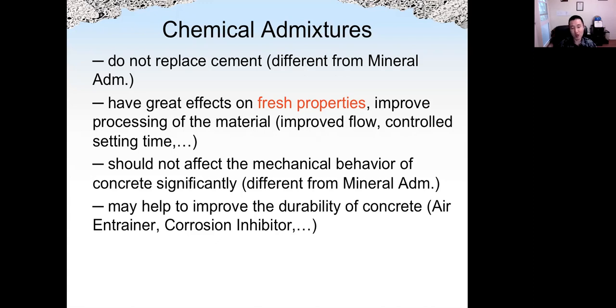So chemical admixtures do not replace cement. So this is one of the major differences from mineral admixtures. So for mineral admixtures, for example, fly ash typically replaces 10, 20, 30, or even more percentage of Portland cement. Okay, but for chemical admixtures, they do not replace cement. Okay, so they may have a very great effect on fresh properties. They may increase the workability of a concrete, for example, or change the setting time, either increase the setting time or reduce the setting time.